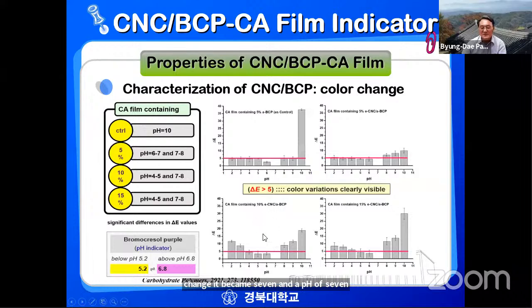And the 10% is much better than 5%. As you see here, between pH 4 and 5, there are big changes in color, and also there are changes between 7 and 8. We can detect the colors of this film above pH 8 over here.